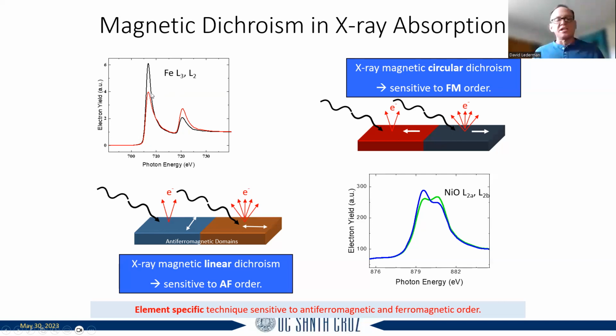For most metals that are not magnetic, the right-handed and left-handed polarization would have the same signal, and then you would say, oh, this is not magnetic. But iron, for example, would look like this. This is the L3 and the L2 edge. Then you can do element-specific measurements, because you could tune it to the ferromagnet or the antiferromagnet. If the ferromagnet is cobalt and the antiferromagnet is iron fluoride, then you can measure the magnetic properties of both materials separately. So that's what we did here.